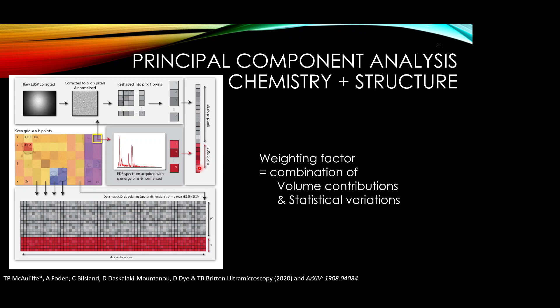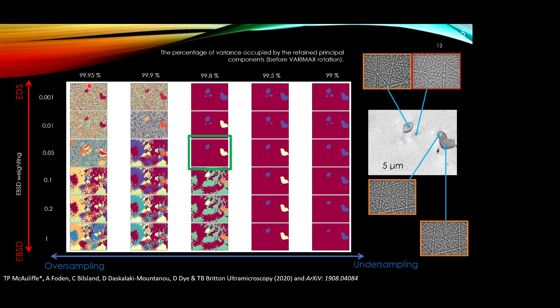To tune this, we run a semi-physical approach as described in Tom's paper. In this method, this shows the weighting components of how much EBSD signal to use versus EDS signal. The top is weighted EDS focus, and this is saying how many characteristic signals we're allowed to use. This is more characteristic signals so it looks noisier, although you're just labeling this afterwards. Although these may have two different labels as shown here, when you measure them by matching to crystal patterns, they may come out as the same orientation or crystal structure. You're looking for a sweet spot, and there's a statistical approach described in Tom's work that enables us to get out that the phases are uniquely described, even when there are two very similar crystal structures that are connected. This is a decomposing carbide after some thermomechanical treatment.